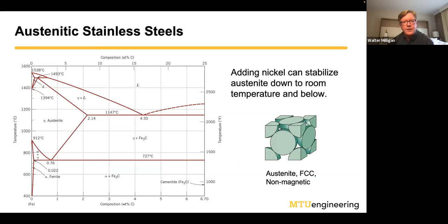The austenitic stainless steels are interesting. What the austenitic stainless steels are is, if you can add nickel to your steel, then you can take this austenite phase here, which is not stable below 727 degrees C for a plain carbon steel. And the 727 degrees C, that would be glowing red hot in the furnace, starting to glow red hot anyhow. So if you went below that, the austenite is no longer stable. However, if you add nickel and chromium, you can stabilize the austenite phase so that it's actually stable at room temperature and below.